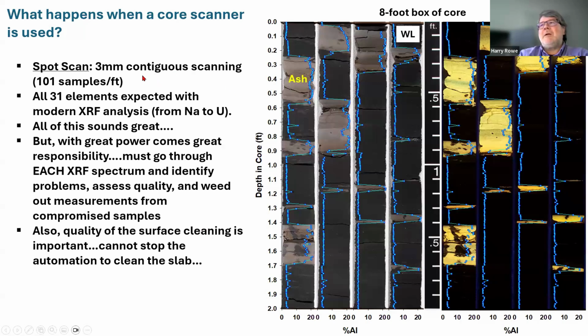But what if we could use a core scanner? This is a core scanner with a spot size of about 3 by 4, and it's a contiguous measurement, about 101 samples per foot. This was a study that we did. We're trying to understand ash, mud rock intervals, and really most people doing this right now are focused on defining that linkage between the geochemical and mineralogical variations and how they can use that to predict the mechanical properties. Also, some of the fluid compatibility issues that are seen in these ash rich mud rock strata.